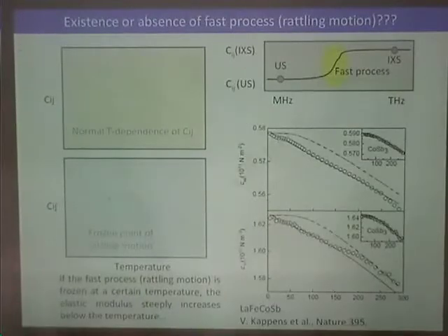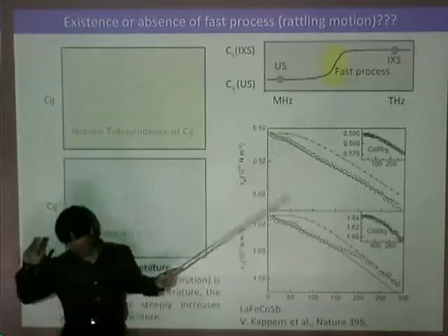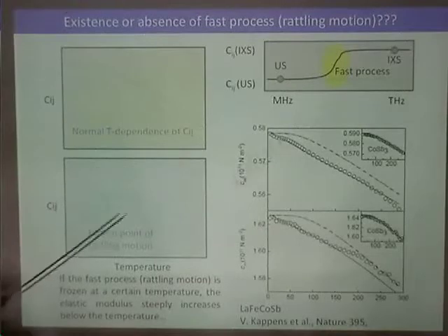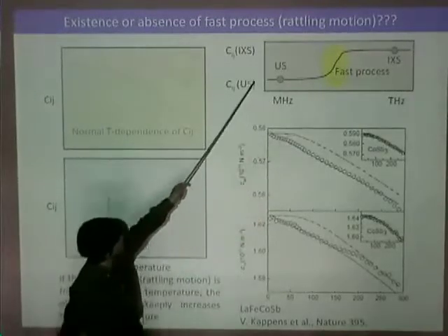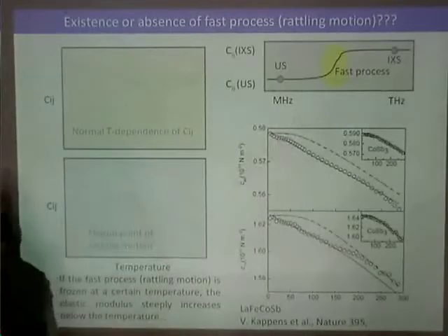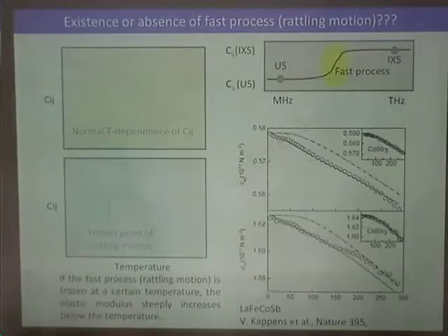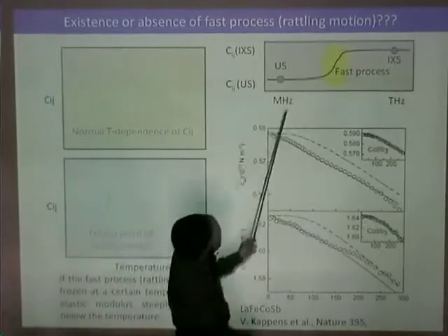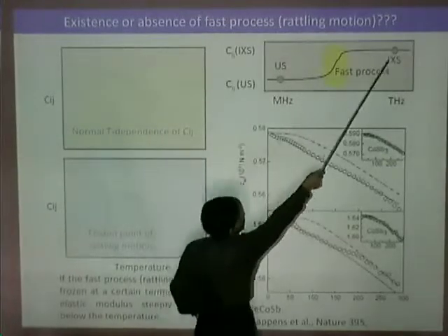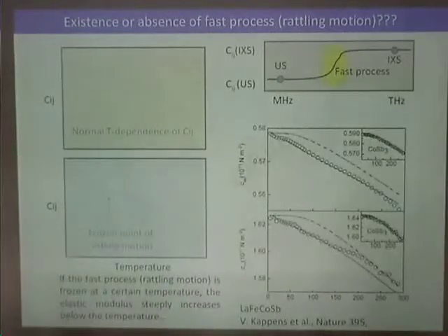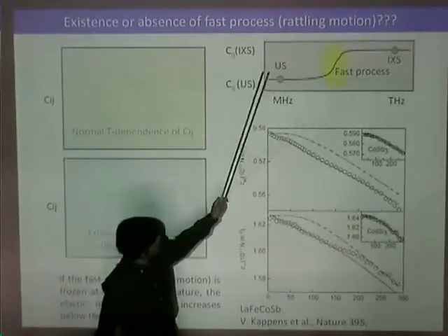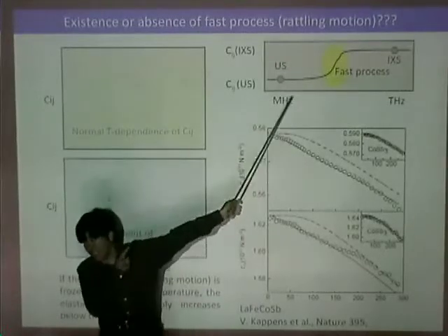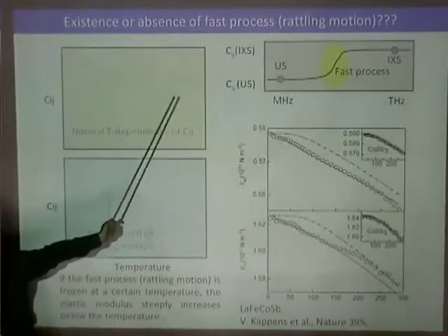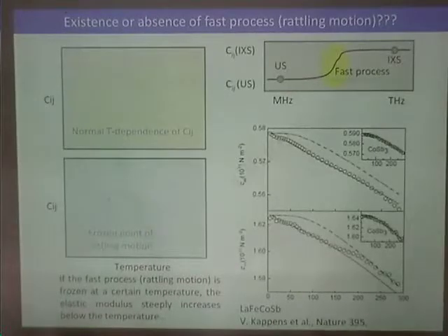So if some faster process exists between the megahertz and terahertz frequency ranges, the ultrasonic vibration elastic constants are inevitably lower than the IXS elastic constants. So in order to check whether this is absent or present, we have to do elastic constants measurement at low temperature.